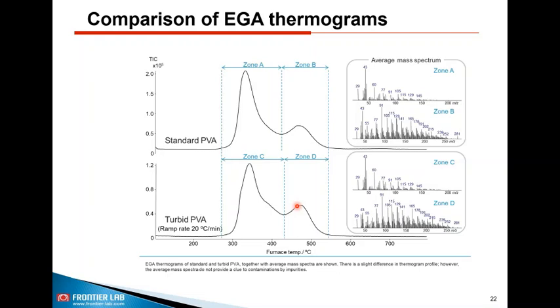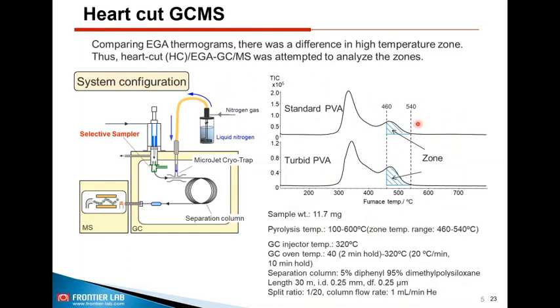So instead of doing a multi-zone or heart cut, what we thought would be good, because we find difference only in this zone, is to do the heart cut for this particular zone, for which you need to use a configuration like this. So you have a GC, then column, then you have micro furnace, and also the selective sampler and cryo trap, particularly to ensure that you are not losing any information. Okay, these are the analytical conditions which I am not going to read.